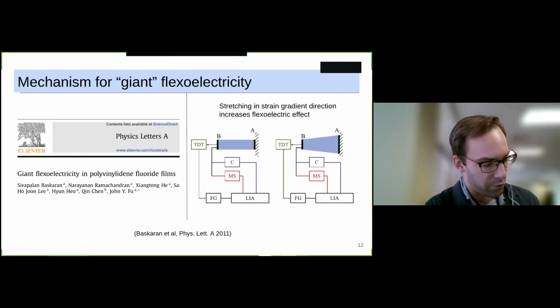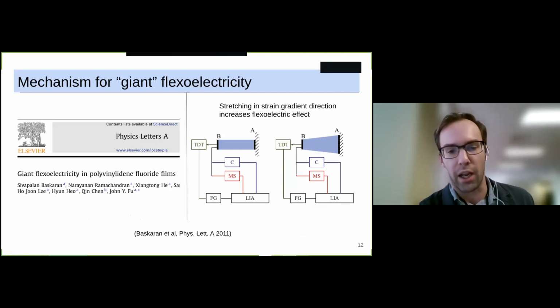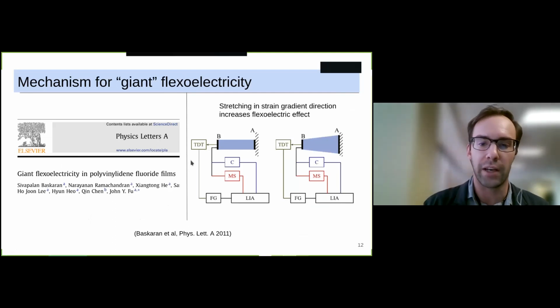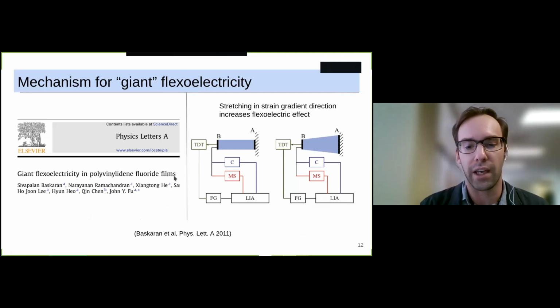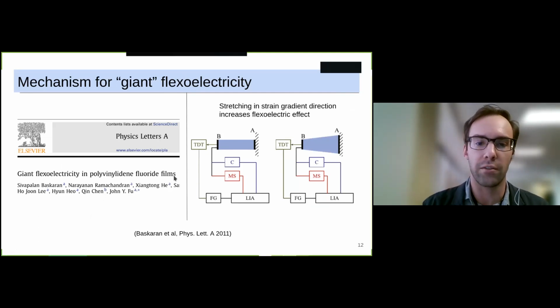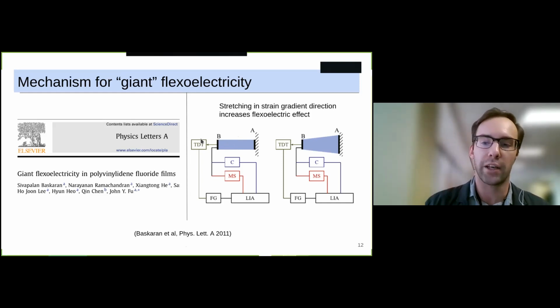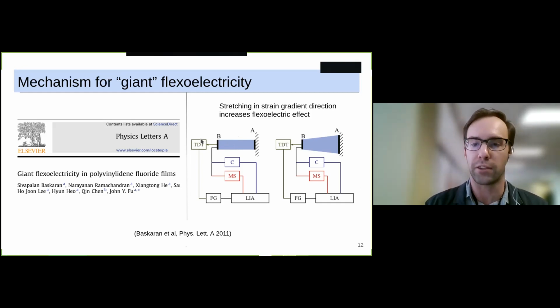What's super interesting, and we didn't realize this until after the fact, is that the equations agree with a very surprising experimental result. If you take a lot of these elastomers and you stretch them in the strain gradient direction before you measure, you apply the strain gradient, and then you measure the flexoelectric effect.